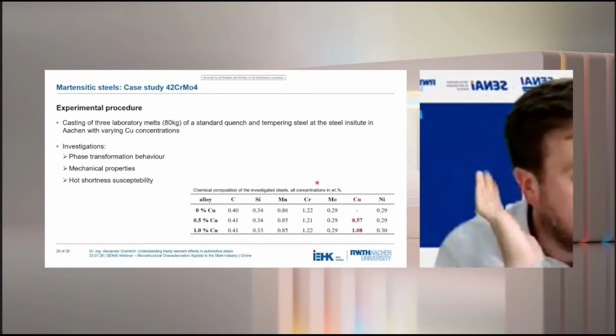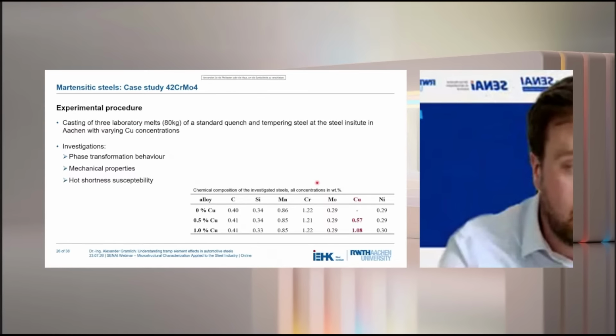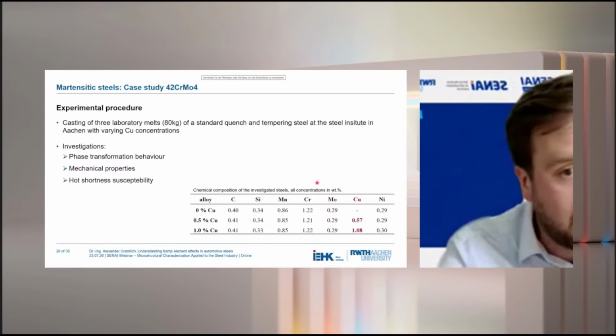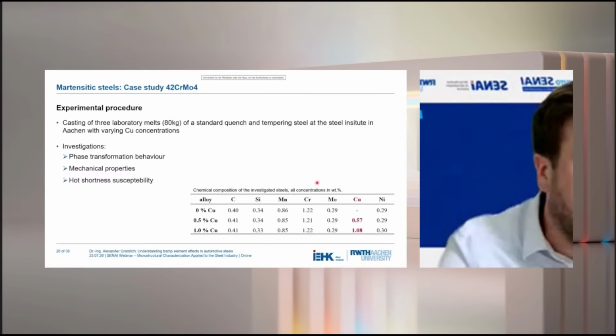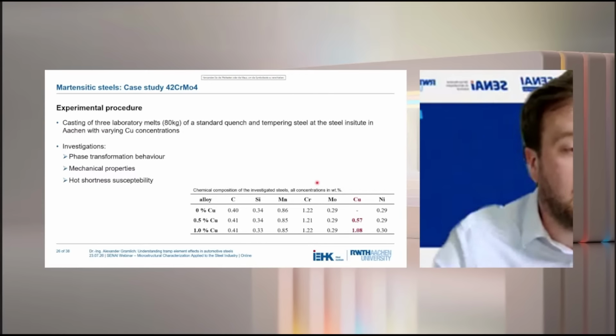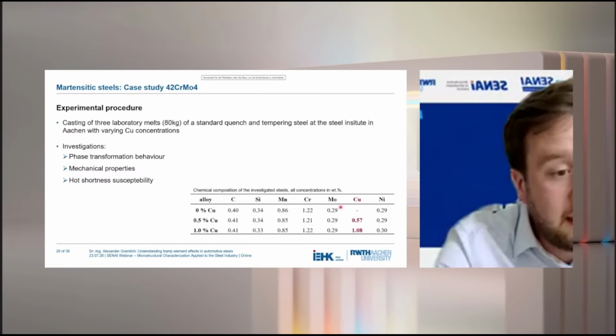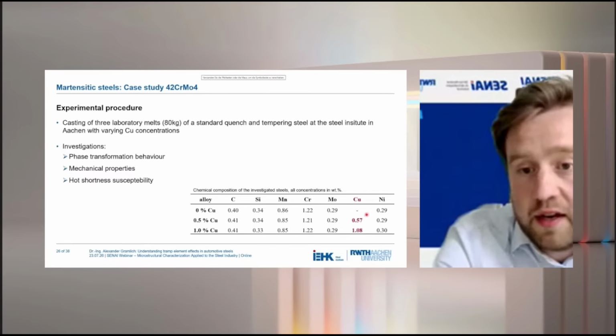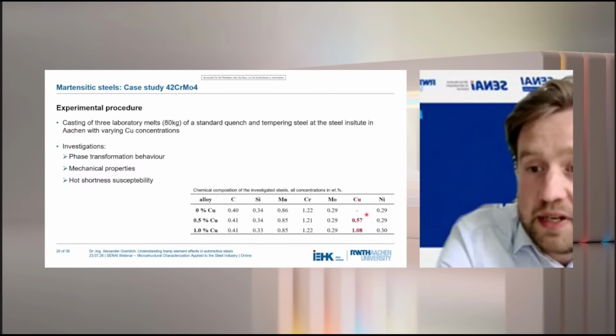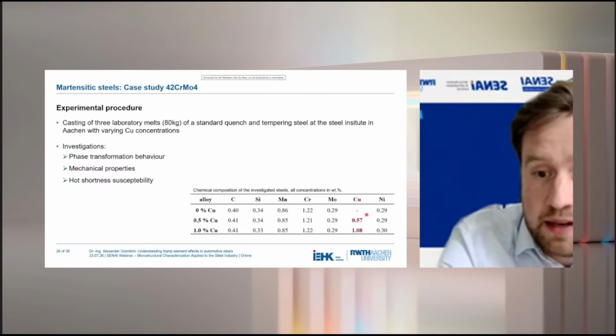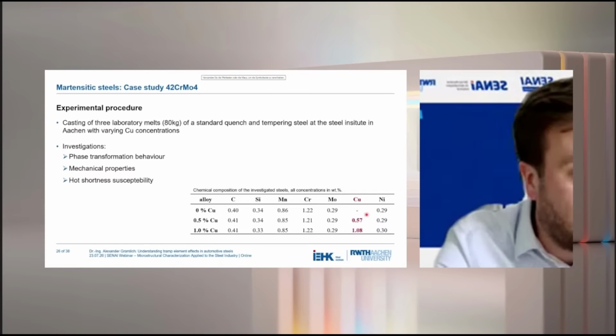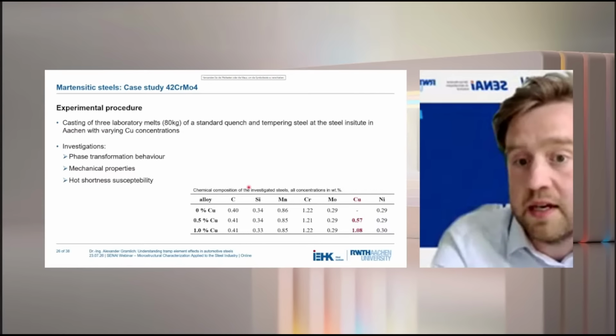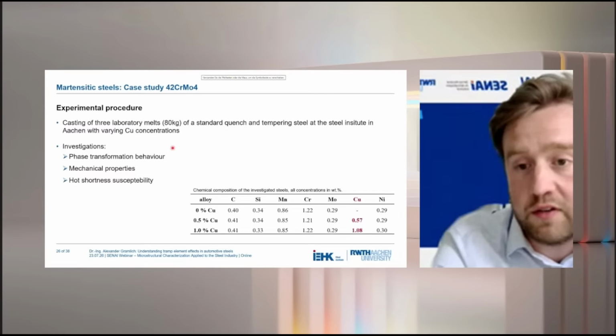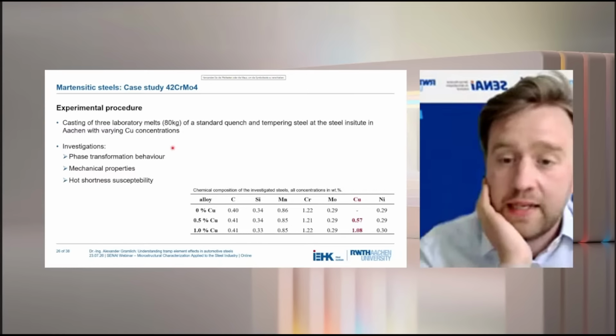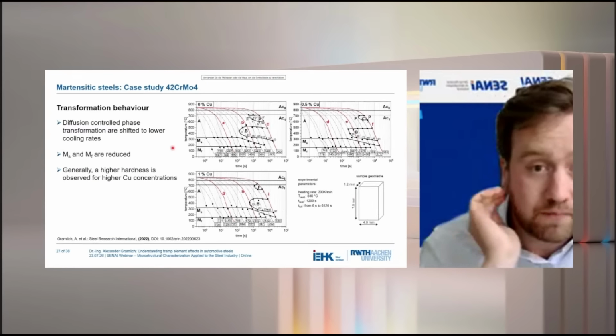And what we are doing, similar to what the colleagues at SENAI are doing, is we're usually producing our own lab melts up to 80 kilograms. And in this case, we varied the copper concentration and added 0.5 and 1% to it. And we investigated phase transformation behavior, mechanical properties, and also the hot shortness susceptibility. But I will focus here mostly on the phase transformation behavior and the mechanical properties.